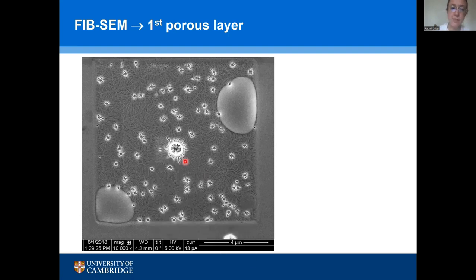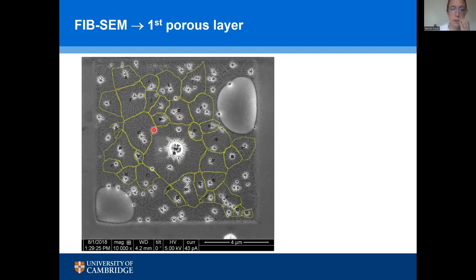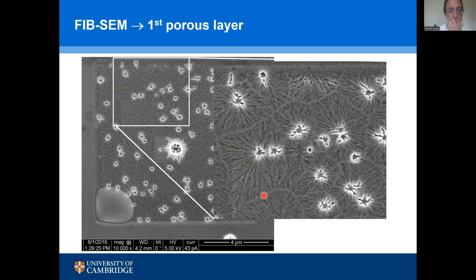And then we have this great big hole in the surface, and we immediately notice that it's made a bigger domain of porosity than the other dislocations that we've seen elsewhere. We can pull out these domains quite nicely, and zooming in on them, we emphasize that for this first porous layer in this area, the etching really happens via this dislocation pathway.